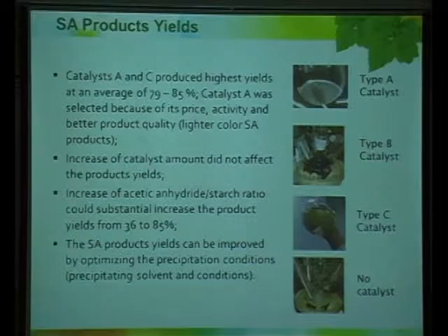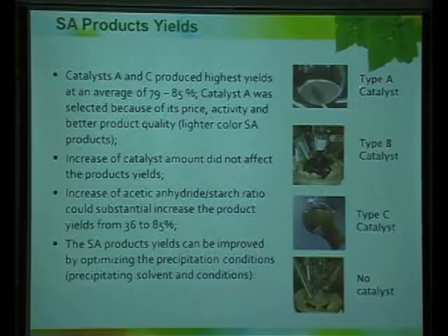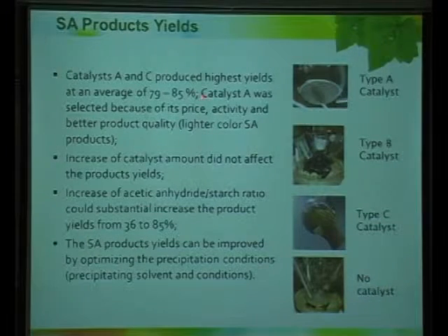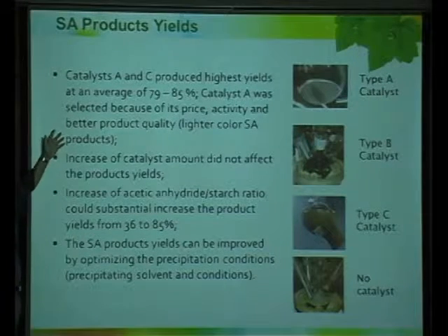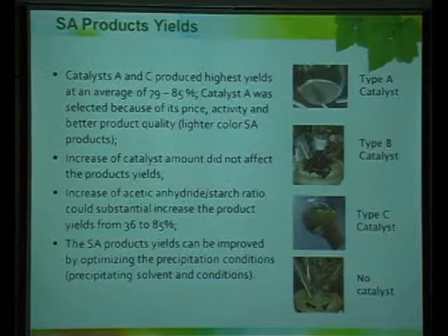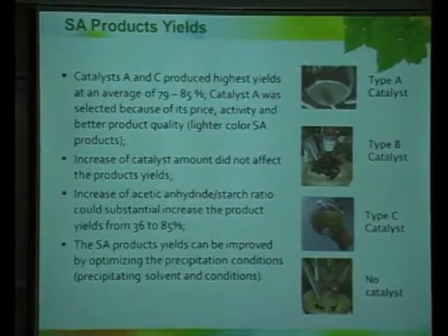And this slide just summarizes the performance of different catalysts. Because the patent is still under application, we are not able to say what type of catalyst, but we separate them into groups A, B, C so we can show the difference. Group A, catalyst A, actually produces a very high yield, 80%, 85%, which is very high. And this catalyst has advantages: it is less expensive and can also be reused after the reaction. Catalyst C is similar, but a little bit more expensive. So we choose catalyst A as the more promising catalyst. I don't want to go into more details here.